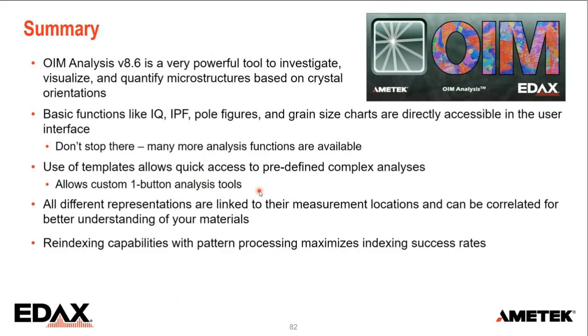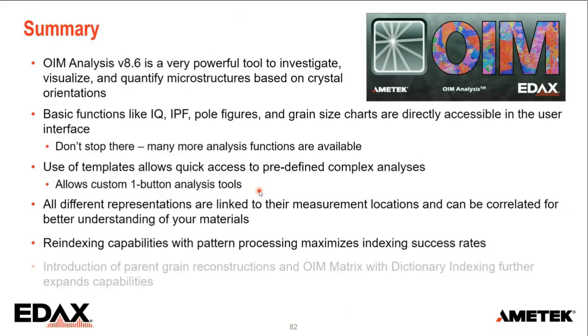Since the introduction of OIM Analysis 8, we have the re-indexing capabilities in there that have been developed more and more until what we have now in OIM Analysis 8.6, and that really maximizes the indexing success rates. So that is optimizing your image processing, the Hough transform, maybe the phase, but also dictionary indexing. So there's a lot of capability in there to even get good data out of materials that are really difficult to get good diffraction patterns from.